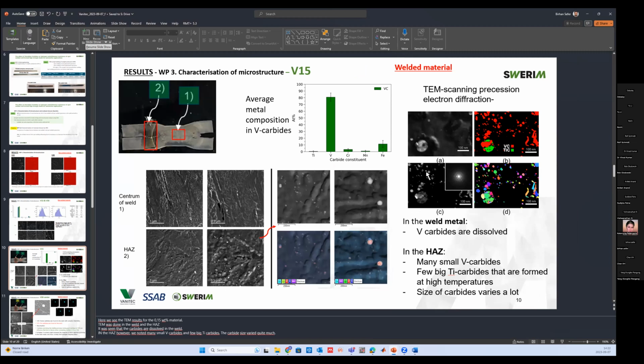The next are TEM results to compare what is happening during the spot welding process. Here in this corner you have an illustration of where we took the carbon replica. We analyzed the center of the weld and close to the heat affected zone. What we have observed is that we don't see any particles in the center of the weld. Most of the particles, vanadium carbides, were dissolved and disappeared from the weld, but we could still see them in the heat affected zone. With the scanning precession electron diffraction method, we could even distinguish whether we are talking about vanadium or titanium carbides. In this particular case, most of the carbides in the heat affected zone are vanadium carbides, and the larger ones are titanium carbides.